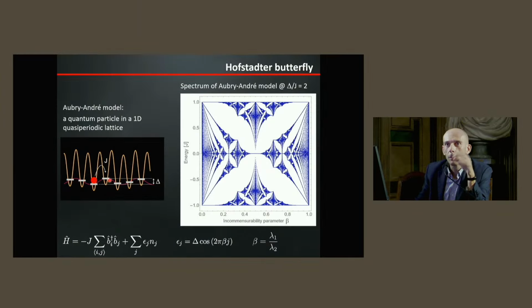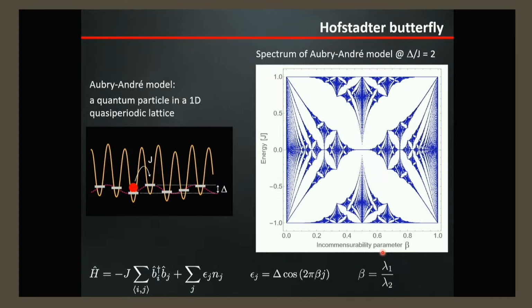...the model of particles hopping in this kind of quasi-periodic crystal, and you consider the energy spectrum of these particles—quantum mechanically, what are the energy states allowed to these particles—you end up with this very nice spectrum here. So on the horizontal axis you have this incommensurability parameter beta, that is the ratio of the two wavelengths, lambda 1 and lambda 2.